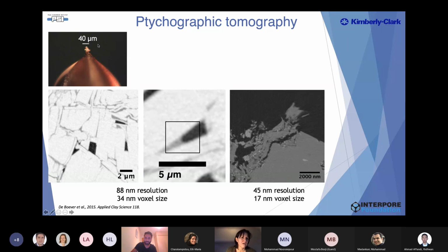So here we took a small sample and scanned it at a certain relative humidity, and we wanted to see the contact angle inside the pores, which was important because we were focusing also on the effect of the contact angle. We were very happy because we could see resolutions of 88 nanometers and voxel sizes in this case up to 17 nanometers.